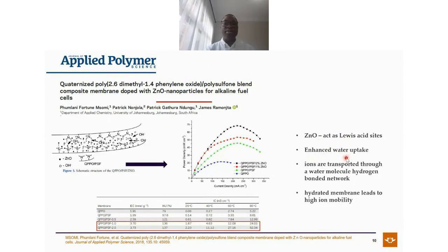Why is that important? Well, with the fuel cell and the membrane, we have two transportation mechanisms, which we're still going to discuss in detail later. We have what we call a vehicular method, where this OH minus is transported through a membrane via hydrogen bonding, and that can happen in the presence of water. And also what we call the hopping method, which we've already spoken about. So what we found out was that ions are transported through a water molecule hydrogen bonded network due to the higher water uptake. And also a hydrated membrane leads to higher ion mobility.